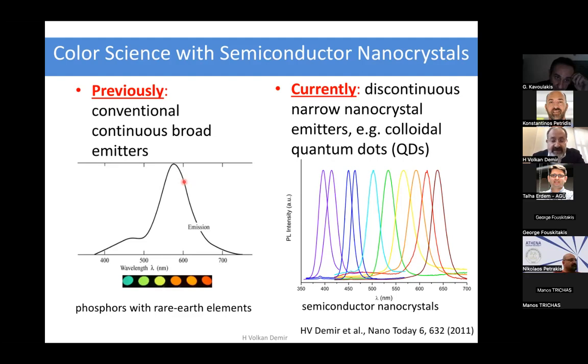And this is the typical behavior using rare earth emission centers with many atomic transitions hosted in a phosphor material. This is the garnet, and creating very broad emission. The difficulty is with so many atomic transitions, it's difficult to fine-tune the spectral details. And this then manifests itself as limited photometric performance. On the other hand, if one would use discrete emitters such as semiconductor nanocrystals with the strategic combination, one can actually generate quite high quality white light with high photometric figure of merits. And that's the problem we have been looking into.